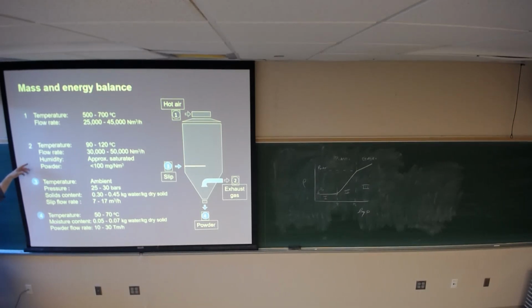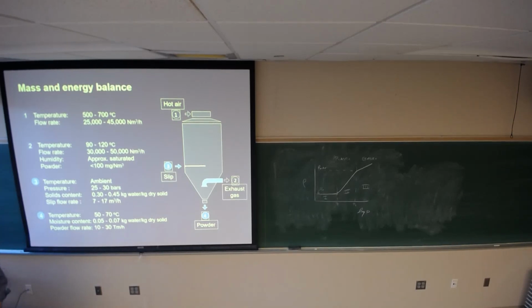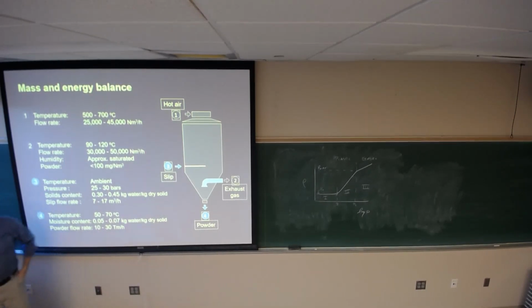and then the number 2, the flow rate coming out the exhaust back, is this difference. You're basically increasing the volume of air out of the system. So your air that's coming in is 25 to 45 cubic meters per hour. What's going out is 30 to 50. So you increase the volume of air leaving the system by, in this case, you would say 17%, right? If you take the difference, or 10% for 45 to 50, okay? That increase in volume is water evaporated from the spray or granule. And then last is you get granules out that are 5 to 7% water. That goes into the press.